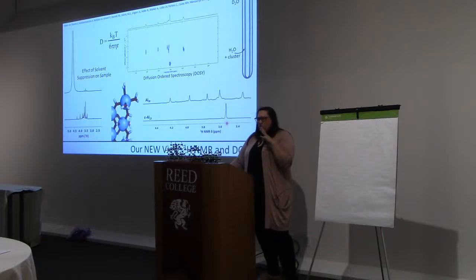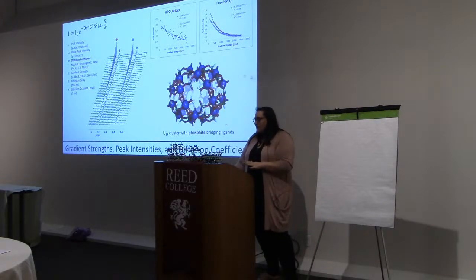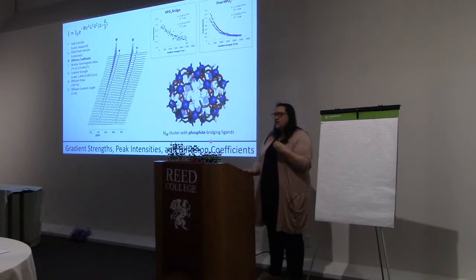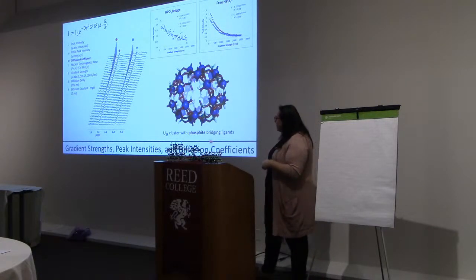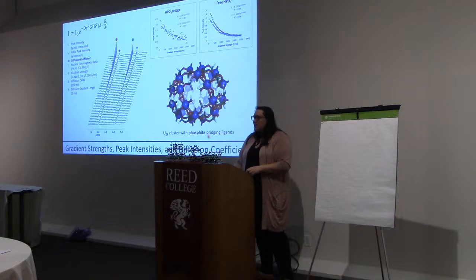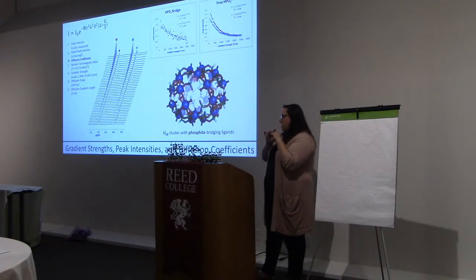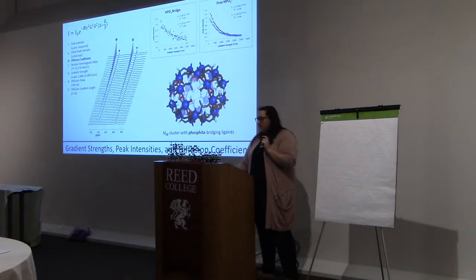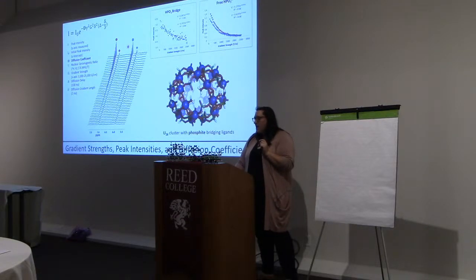So how does DOSY work? Just a little bit more. Here is a uranium cluster that I studied in my postdoc that I'm just going to use as an example. This uranium cluster had phosphite bridges. So between the blue uraniums, there are phosphites connecting them. That has a nice phosphorus hydrogen bond. And so the phosphorus was splitting the hydrogen, so we get doublets here. Now, there were free phosphites in solution and phosphites that were bound. And so when you do DOSY, you do a series of proton NMRs at different gradient strengths, and then it uses this equation.